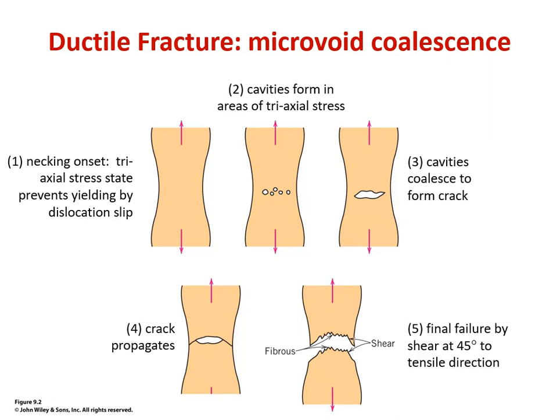The outer skin of that material is in a less triaxial stress state because it's on the surface. So it is seeing more just pure uniaxial tensile stress. So its final failure is at 45 degrees to that uniaxial stress, the same kind of idea we went over with the critical resolved shear stress in our strengthening mechanism section. If we look down at the failure surface, it usually has a lot of topography. It'll have a fibrous sort of appearance, and it'll also have little round cups that correspond to those original microvoids that coalesced.